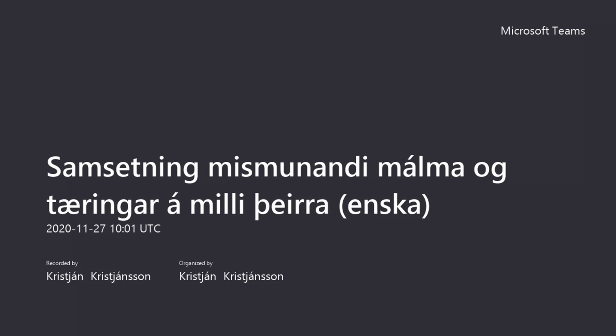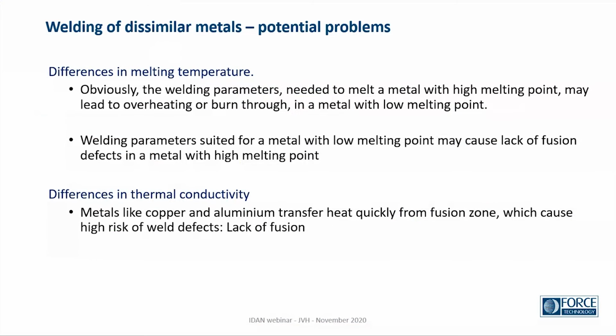If we use welding parameters suited for metal with a low melting point, on the other hand, you may cause lack of fusion defects on the part with the higher melting point. Another thing might be the differences in thermal conductivity. Metals like copper and aluminium transfer heat quickly from the fusion zone, which causes a high risk of welding defects, such as lack of fusion.